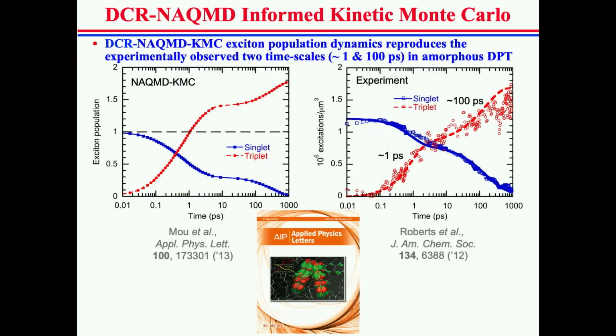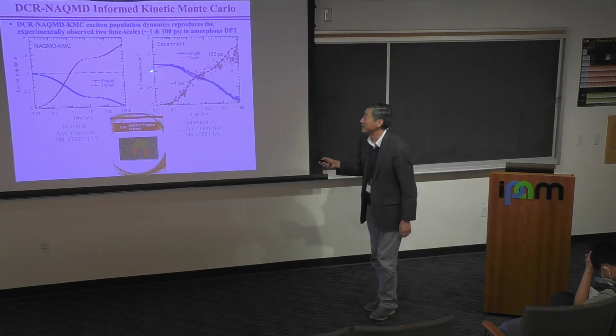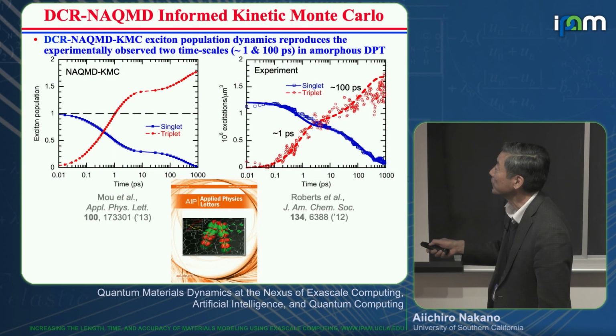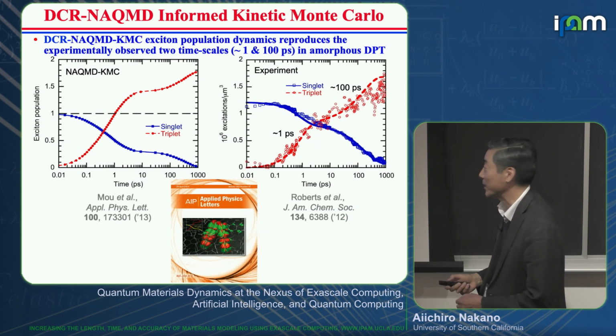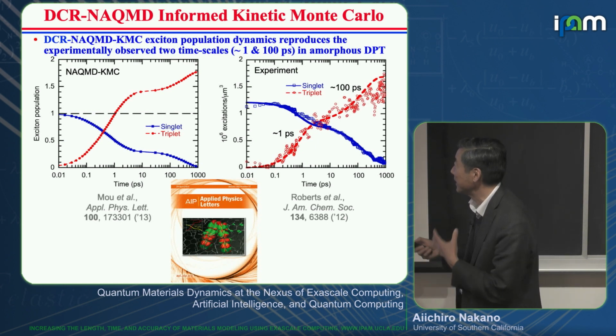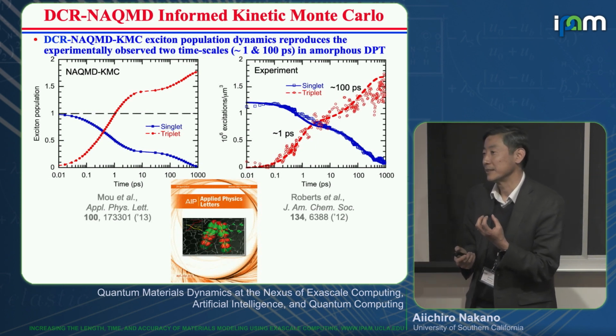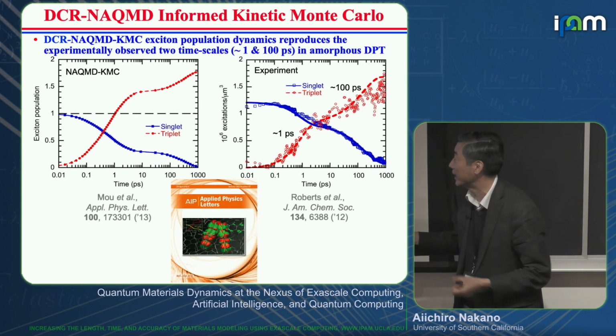Eventually, we observe the fission. So that's the NAQMD divide and conquer. And then this is the computed population of spin singlet and spin triplet excitons as a function of time, no fitting parameter, which agrees very well with the pump-probe experiment at USC. Especially, we reproduce these two time scales around 1 picosecond and 100 picoseconds. The same as experiment, we are able to explain it as a consequence of a singlet fission hotspot in the